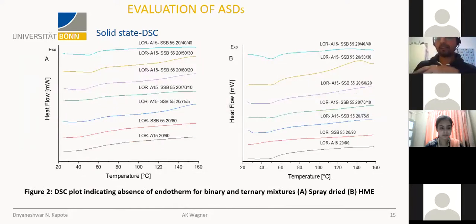After you get the ASDs, we also checked for the absence of an endotherm, because if you have a small amount of API which is not dissolved or recrystallized, you can observe it in DSC. In our case, the API melting point was 137 degrees Celsius. At that point, no melting endotherm was observed, thus confirming that the amorphous solid dispersions are formed using hot melt extrusion as well as spray drying.